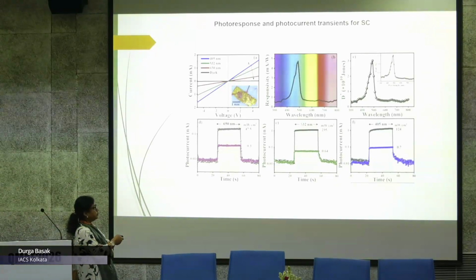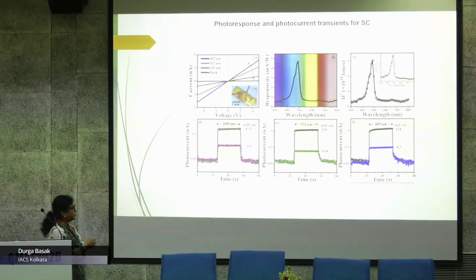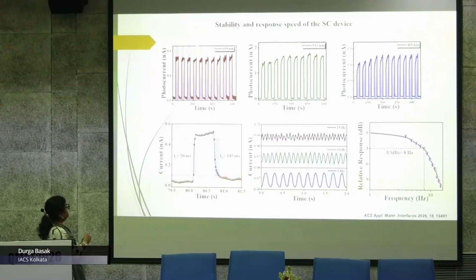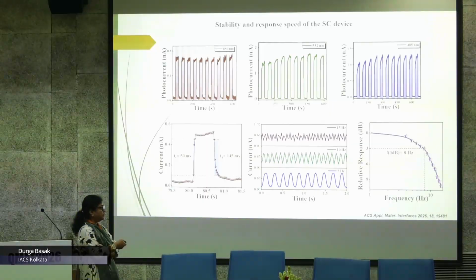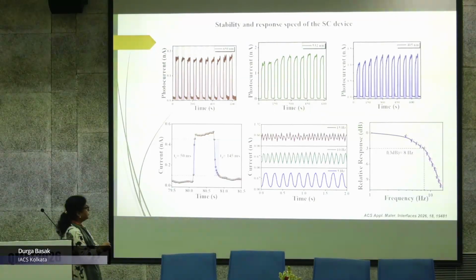It happens the same in case of 532 and 405 nanometer. That means it has sub-band gap defects caused by the sulfur vacancy. And these are the cycles showing the stability and the response speed of the single crystal device. From here we have measured the time of response and decay, which are 50 millisecond and 145 millisecond, and the frequency modulated response of this single crystal in the time domain is like this. From there we have found that the -3 dB frequency value is 8 Hz in case of single crystal.